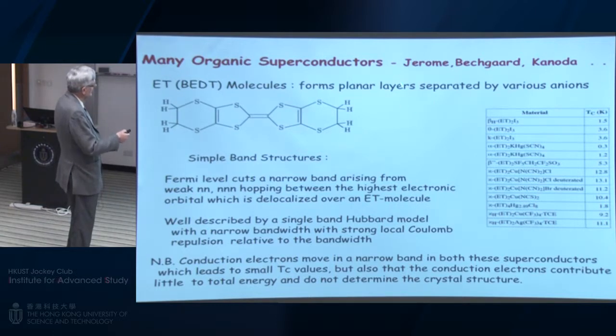The other material class is these organic superconductors, where we have large organic molecules which can arrange themselves in layers or linear stacks. They get a simple band structure because the band structure is associated with an outer electron which is delocalized over the whole big molecule. So the Fermi level cuts through a narrow band of electrons that are delocalized over the molecule. And you can find, again, many of them. Here's a list of ones made out of this particular molecule, the so-called ET molecule. Some of them get up to 13 Kelvin. But again, there are a lot of them.